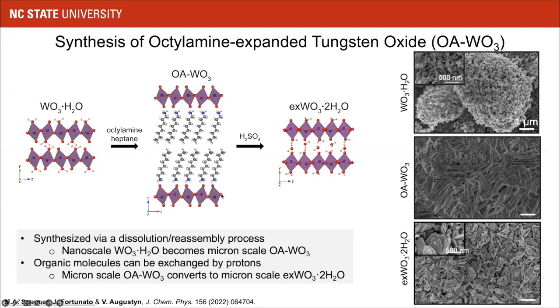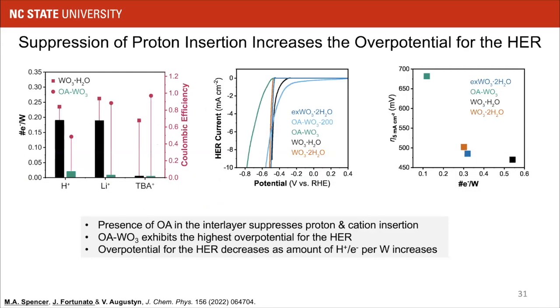Then if you expose this material to sulfuric acid, an ion exchange process does take place and you form the dihydrate form of the material, but on a micron scale. So now we have several materials that we can use to probe how proton insertion affects the hydrogen evolution reaction taking place on the surface. The first thing we note is that with these octylamine containing materials, we suppress proton and cation insertion. Whereas protons and small ions like lithium ions can insert into tungsten oxide monohydrate, once we have octylamine in the interlayer, we basically stop those from intercalating. And both materials are not able to intercalate a bulky cationic tetrabutylammonium.